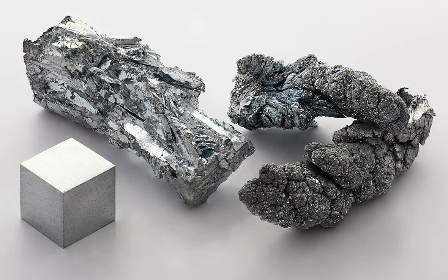In 2009, in the United States, 55% or 893,000 tons of zinc metal was used for galvanization. Zinc is more reactive than iron or steel, and thus it will attract almost all the local oxidation until it completely corrodes away. A protective surface layer of oxide and carbonate forms as the zinc corrodes. This protection lasts even after the zinc layer is scratched, but degrades through time as the zinc corrodes away.